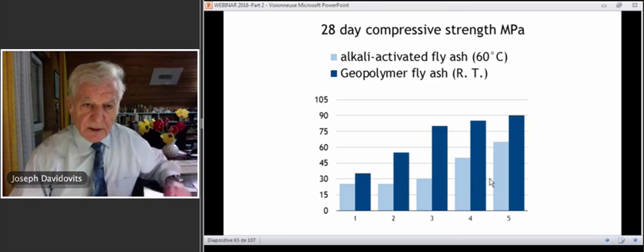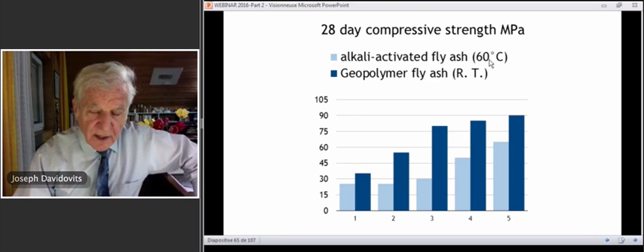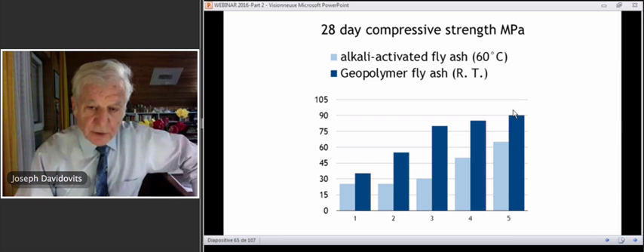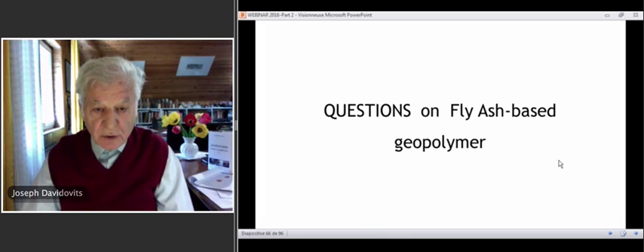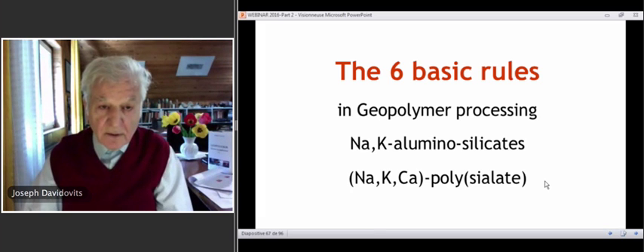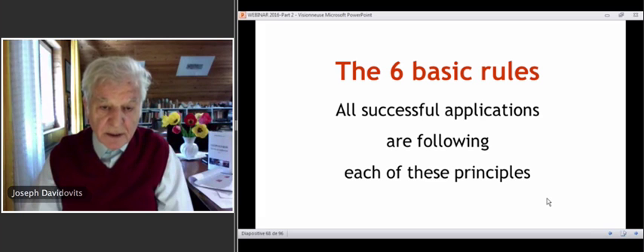And if we compare 28-day compressive strength, alkali activated fly ash made at 60 degrees C for 24 hours, and geopolymer fly ash at room temperature, for different fly ashes, the geopolymer fly ash room temperature hardened material is always better, and quite a bit better depending on the fly ash. I continue because what is important is to understand how to handle all this material. So I present the 6 basic rules in geopolymer processing for sodium potassium aluminosilicate to produce polysialates. All successful applications are following each of these principles.